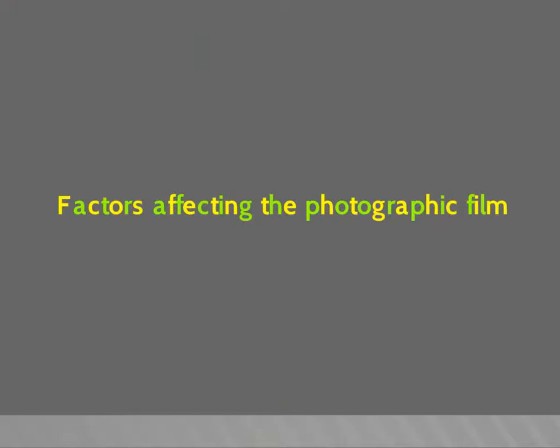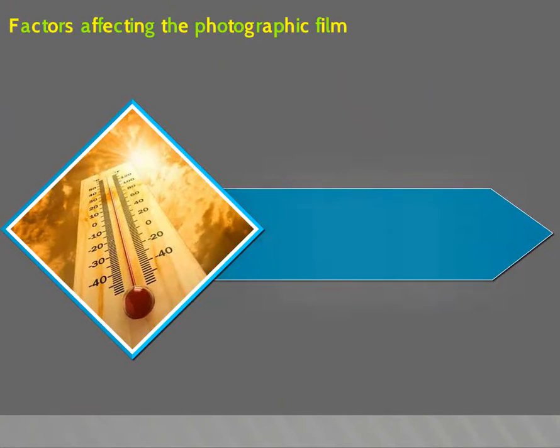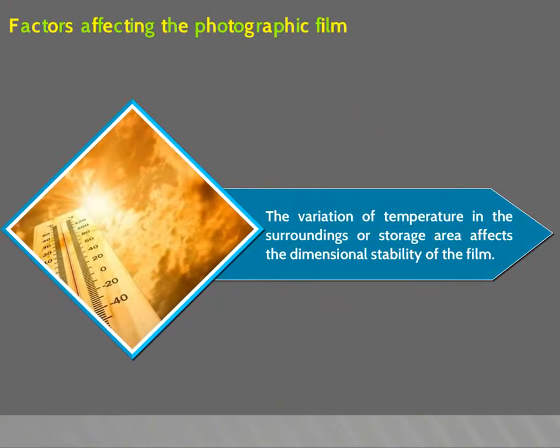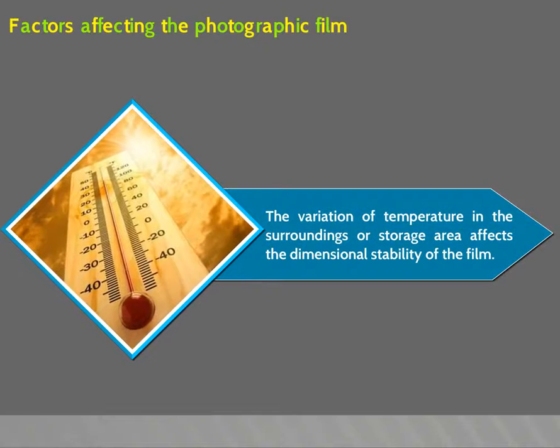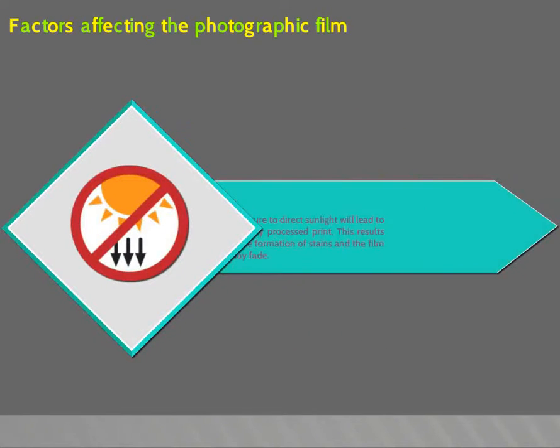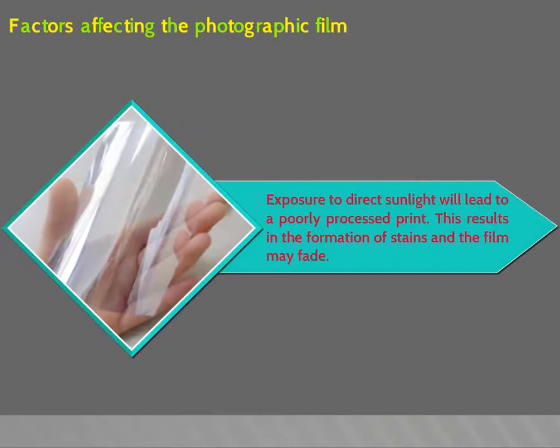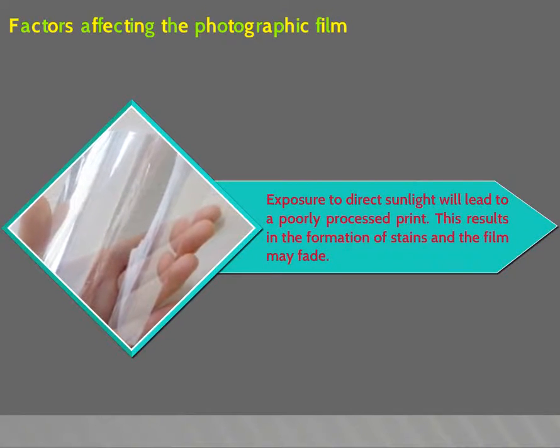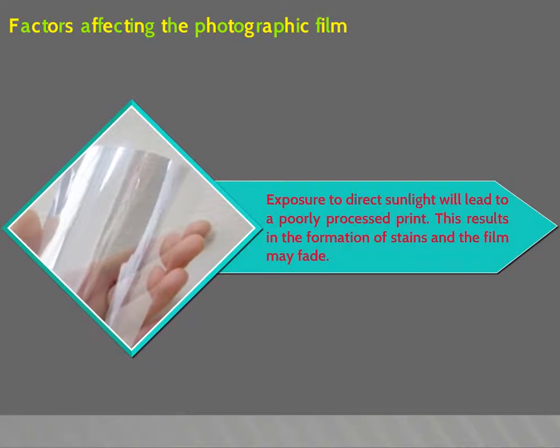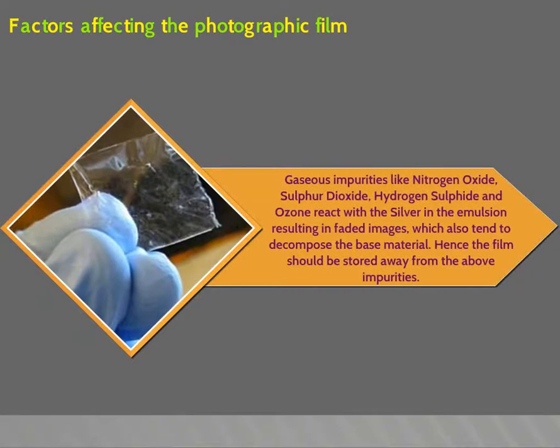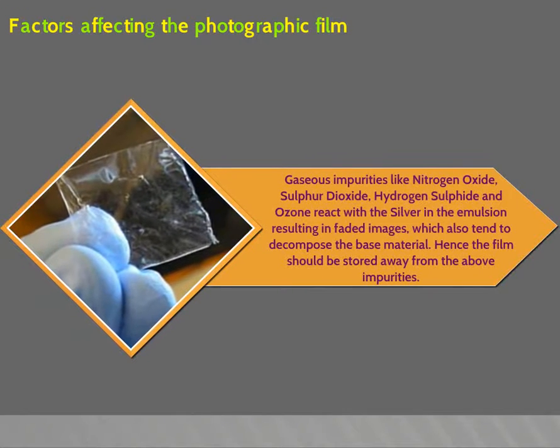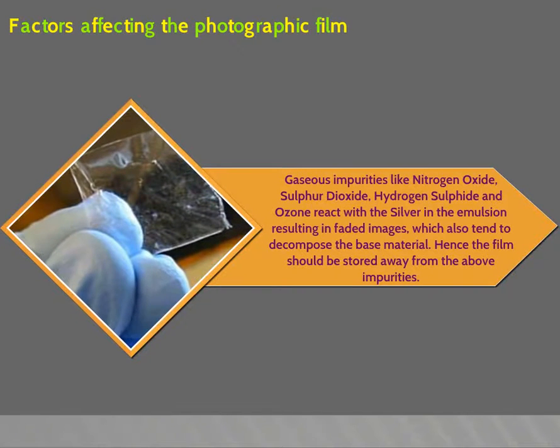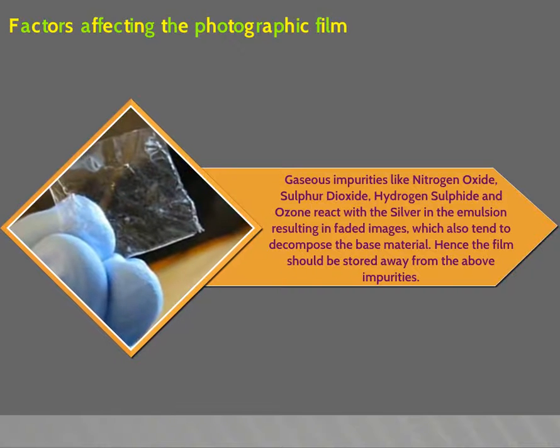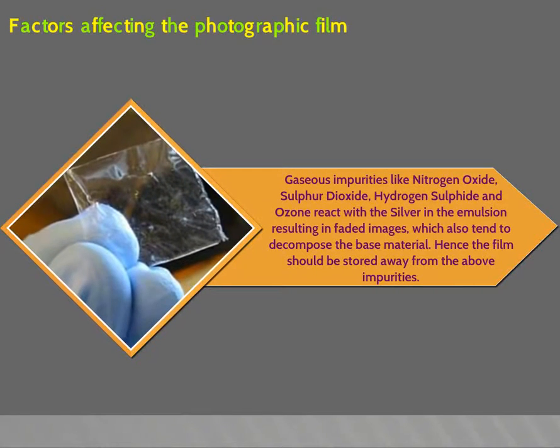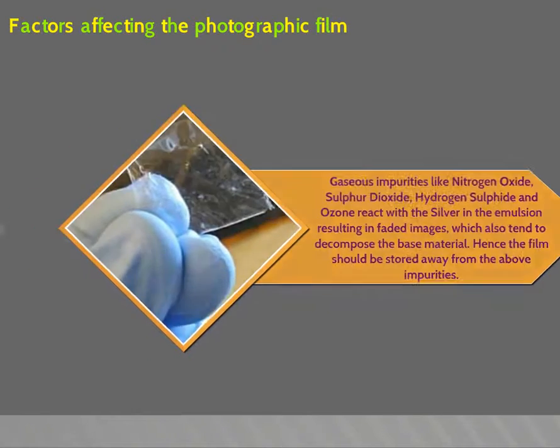Factors affecting the photographic film. The variation of temperature in the surroundings or storage area affects the dimensional stability of the film. Exposure to direct sunlight will lead to poorly processed print. This results in the formation of stains and the film may fade. Gaseous impurities like nitrogen oxide, sulfur dioxide, hydrogen sulfide and ozone react with the silver in the emulsion, resulting in faded images which also tend to decompose the base material. Hence, the film should be stored away from the above impurities.